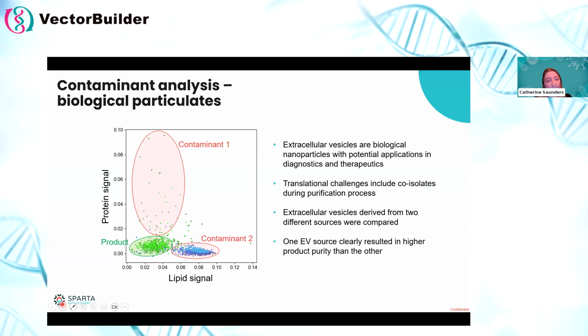And in this case, what we clearly saw from this analysis was that one of the EV sources, the source in green, resulted in much, much higher purity than the other one. So we had much, much more of the product with this particular EV source. And so, you can imagine this kind of analysis. In this case, it was very useful for identifying where these EVs should be coming from in terms of source, but it could also be used for comparing and selecting between different production or purification processes.